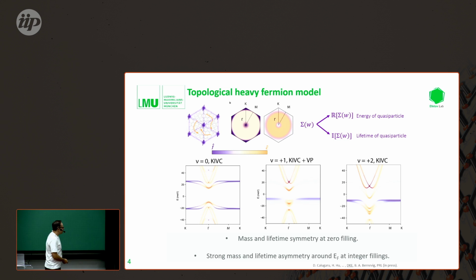So basically for the different ground states that one can compute here, you get robust predictions that for the filling factor 0 state, you basically get symmetric bands for electron and hole excitations, as you can see here. So basically the top and bottom Hubbard bands are more or less symmetric. And when you dope the system, you first excite the dispersive regions of the bands. And the other robust prediction is that if you go to the integer filling states, like filling factor 1, filling factor 2, you basically get an asymmetric electron-hole spectrum, as you can see here.